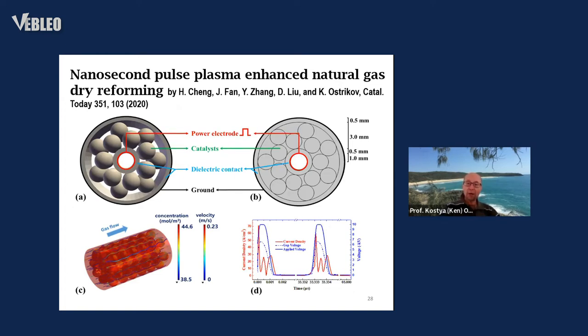You know that we need to convert natural gas that is abundant and produce fuels, some chemicals, and hydrogen fuel. And one effective way to do that is to use plasma catalytic reactions that are based on so-called dielectric barrier discharges that are generated in the tubes that are equipped with two electrodes. One is in the middle of the tube, and the other one is on the outside of the tube. The tube is packed with glass, typically, or other dielectric material beads that are small, typically micrometer-sized particles that fully fill up the space.